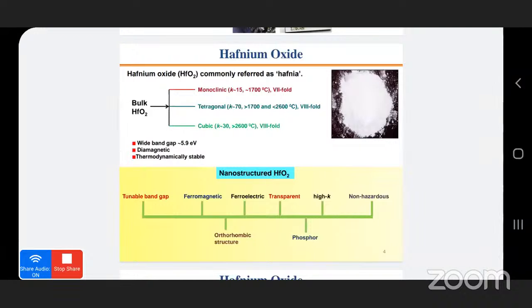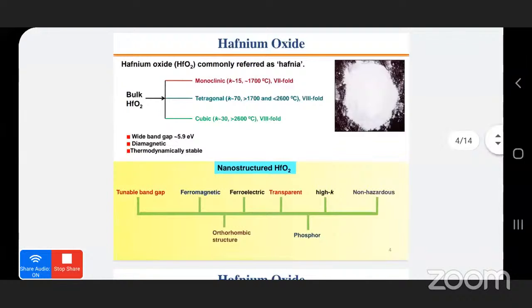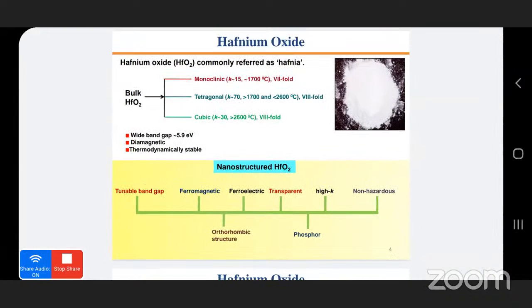Then as we increase the temperature above 1700 degrees Celsius, we get the tetragonal phase. This tetragonal phase has a dielectric constant of 70, and it is stable between 1700 and 2600 degrees Celsius. If we further increase the temperature above 2600 degrees Celsius, we get the cubic phase. Both the tetragonal and cubic phases are high symmetry phases, which are eightfold coordinated with oxygen. Bulk hafnia has interesting properties, such as a wide band gap of around 6 electron volts. The bulk hafnia is diamagnetic in nature, and it is also very thermodynamically stable.